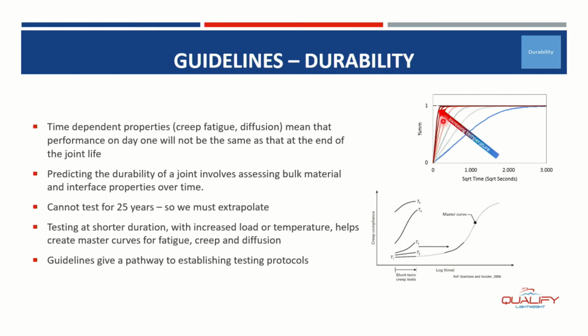You can see here how we might increase temperature to give us different diffusion profiles. And this curve shows us how we use a master curve for creep. So we do short-term testing at different load levels, and then we can time shift that data and create a master curve so that we can predict what's going to happen at the service load, but over time.